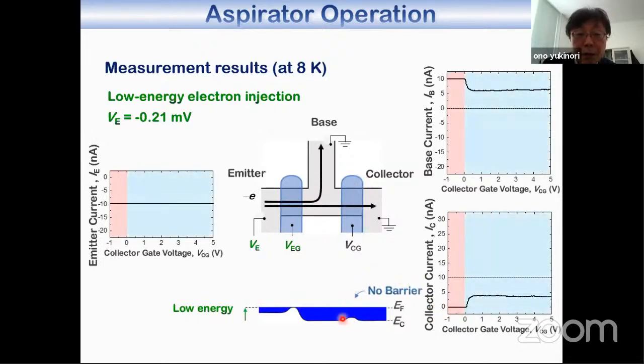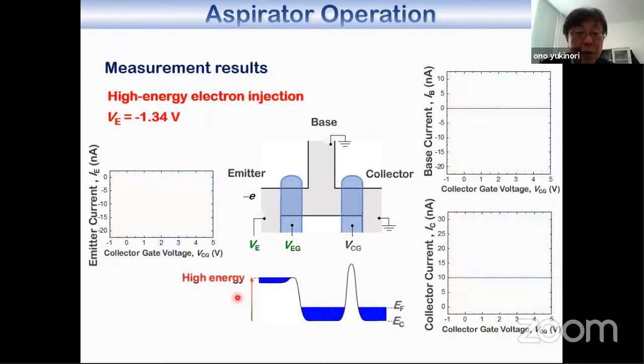However, when we reduce the barrier height, the electrons are allowed to drain to the collector. Therefore, the base current is reduced down to 5 nanoamps, and the collector current increases to 5 nanoamps. This means that in this case, the electrical current is quite normal. Both base and collector have similar current levels. However, if we increase the incident energy, the characteristics were found to change dramatically, which I'll show you next.